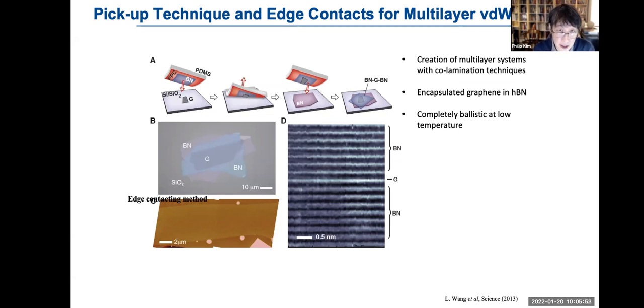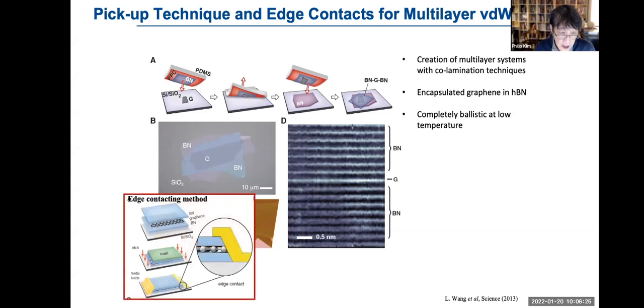And if you do it really carefully, as demonstrated in this work, you have this interface. For example, your graphene is in between boron nitride crystals. As you see, the interface is extremely atomically clean, and no impurity got trapped in between. Atomically abrupt interfaces can be formed in this type of system. Furthermore, you can choose different sequences and different shapes. This also allows us to selectively etch the crystal and make contact in such a way that each individual atomic layer, as long as it is electrically active, can be contacted by choosing the right chemistries and the right recipe of the metal.